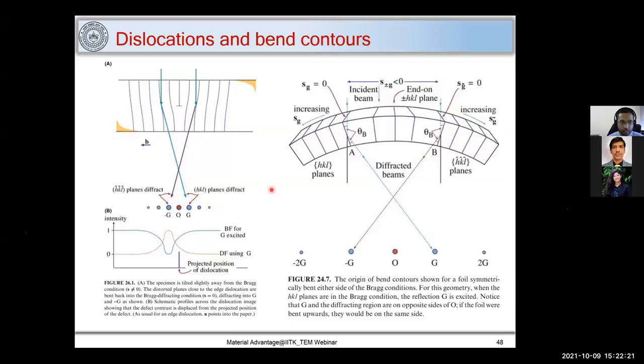Let me give an analogy with the bent contours. Here we have two regions. In this region, you have diffraction occurring in this way, which contributes to G. We have seen earlier what the meaning of G is. And this region will contribute to minus G. You can have this intensity variation in a bright field and this intensity variation in a dark field. You can consider this analogy with the bent contours, where planes are bent, which causes a Bragg's diffraction, contributing to G and minus G.